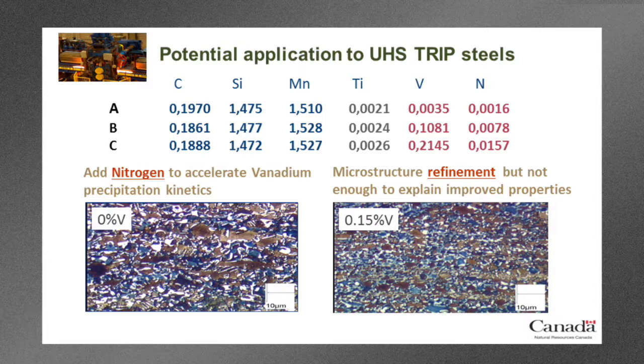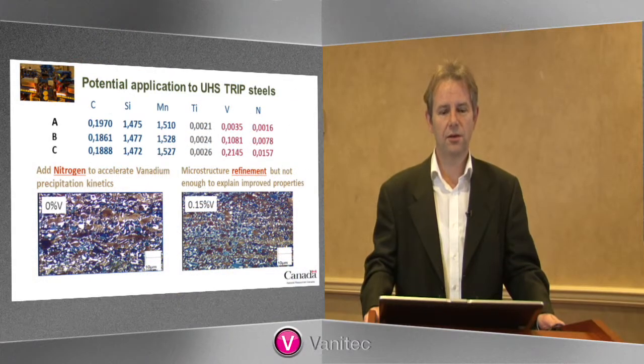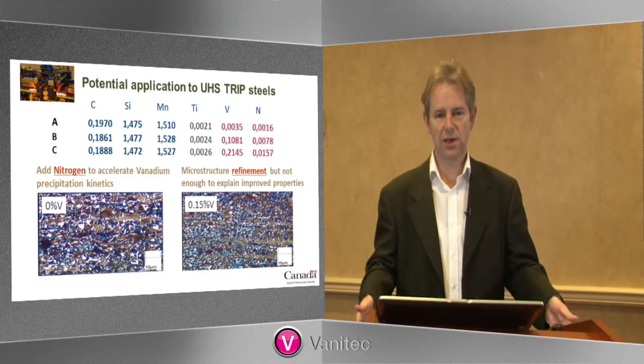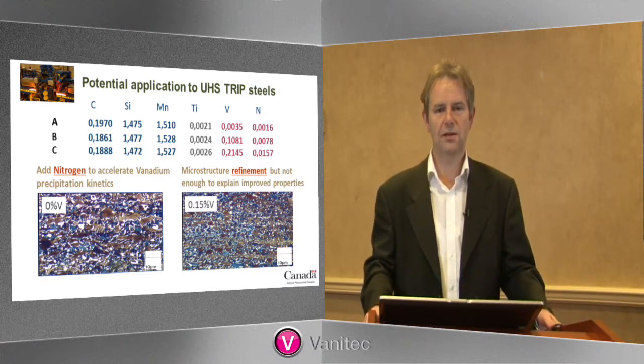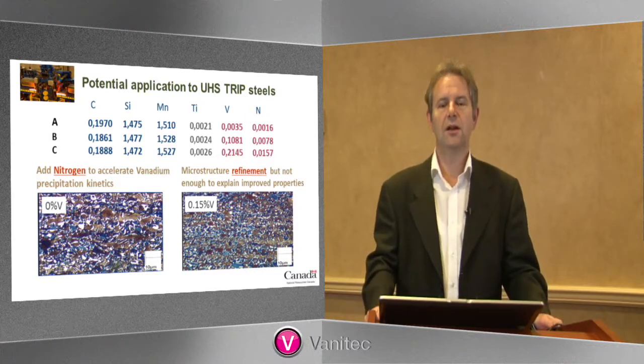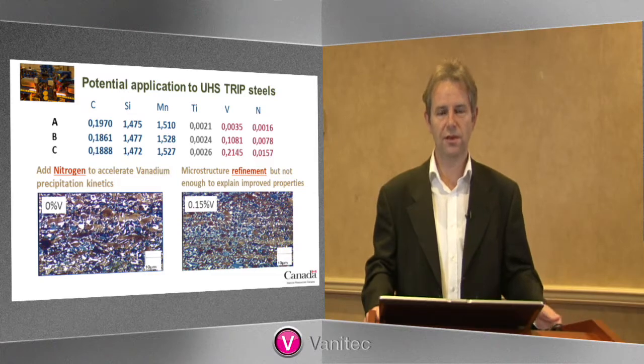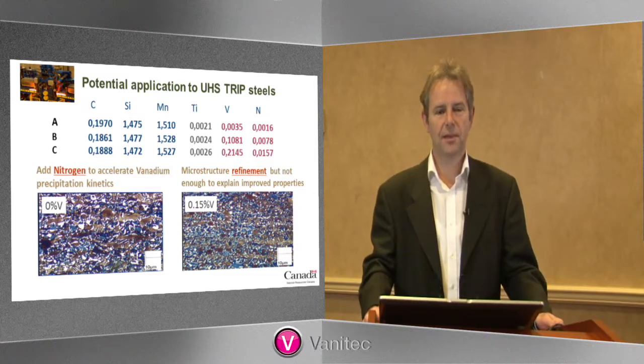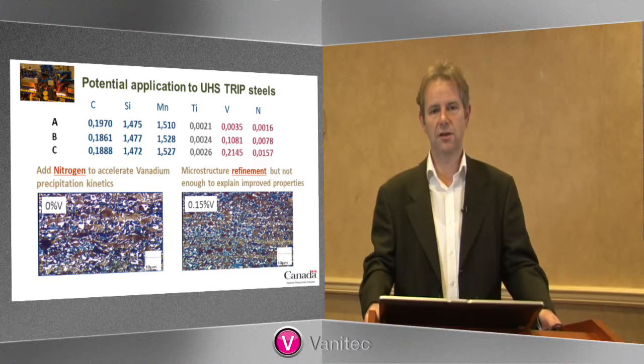So on the left-hand side, the microstructure is the reference steel. We have 0 vanadium in that steel, and on the right-hand side you can see the microstructure once we've added 0.15% vanadium. This is the final TRIP microstructure. It's very much refined. I'll show you later on that the mechanical properties are very much enhanced by this vanadium addition. The question was, is it due to precipitation or is it due to this microstructure refinement? And I'll tell you right now, we ran a structure-properties model that we had developed at Arcelor, and it showed that although the properties were improved and there was a component that came from the microstructural refinement, it wasn't enough to explain the increase in strength. So we do have a precipitation effect.